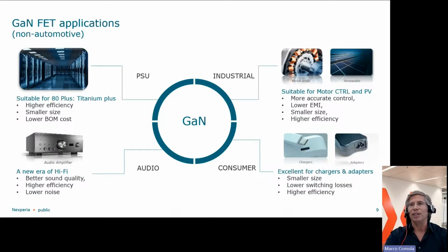And for industry, it is very huge. I just want to focus your attention on the motor driver and solar panel. Gallium nitride is suitable for motor control and PV, photovoltaic, panels. For the motor control, for instance, you increase the frequency, you have a higher bandwidth, so you have a more accurate control. You have lower EMI because you don't have oscillation using the gallium nitride, lower oscillation. And you have a smaller size because, again, it increases the power density, and also in terms of application, you increase the frequency. You then also have a smaller bulk capacity. You can avoid the bulk capacitance, just replacing electrolytic parts with ceramic parts, so you have a smaller size as well. And for both, you have higher efficiency.